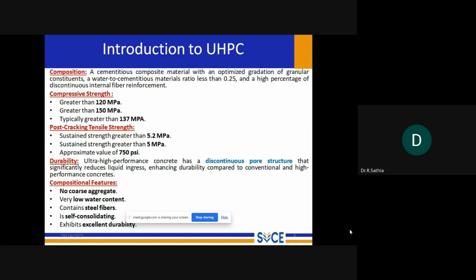So to summarize, UHPC is a no coarse aggregate concrete with a very low water cement ratio, less than 0.25, and the ductility is improved by means of steel fibers. Although the water cement ratio is that low, it is said to be a self-consolidating or self-compacting concrete, and also it has excellent durability.